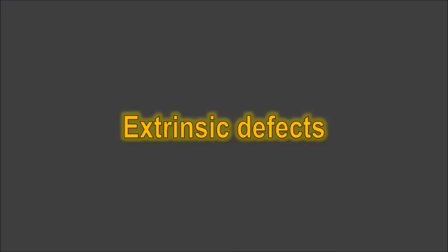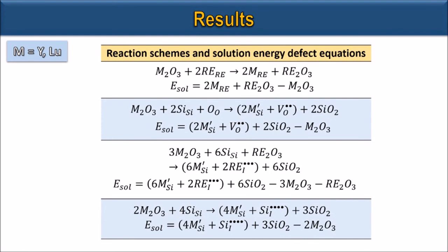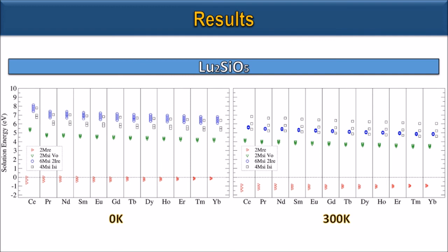So, we will now begin to show some results of calculations of extrinsic defects in these silicates. The table presents the mechanisms considered that involve doping rare earth silicates. For each mechanism, a solid-state reaction is devised and respective solution energy equations can be obtained. The solution energies in both structures were calculated based on these reactions. Here is the graph of the defect solution energies.